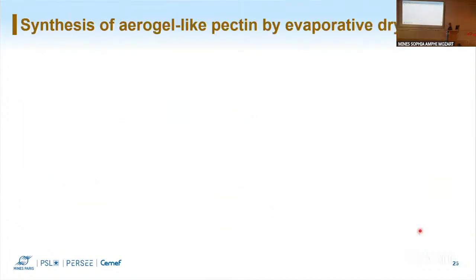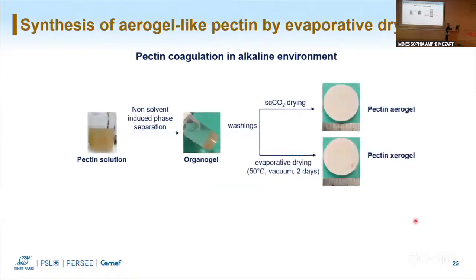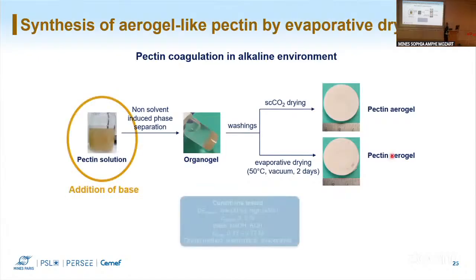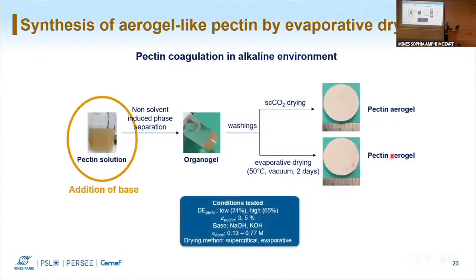And in order to avoid supercritical drying, we try to do pectin coagulation in alkaline environments. So now that scheme changes a bit, there is a new leg here, adding evaporative drying in order to receive xerogel materials. So when I say xerogels, I always refer to materials dried by evaporation, and aerogels by supercritical drying. We worked on the pectin solution and we added base, and we used both high and low methoxypectin. We worked with different concentrations of pectin, 2 different bases for different concentrations of base, and we saw how the drying method is affecting the material properties.